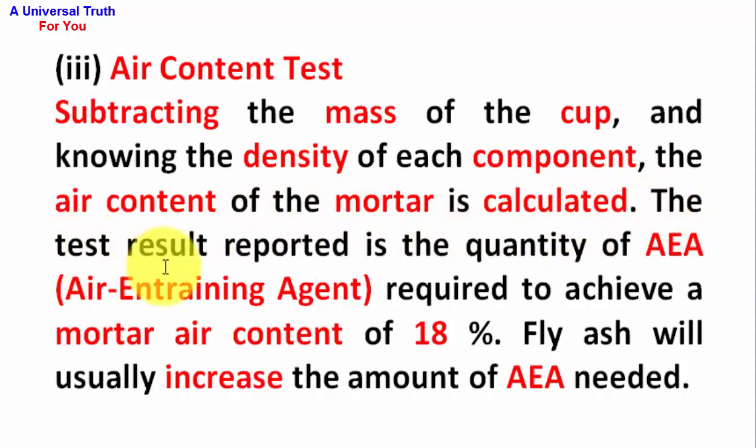The test result reported is the quantity of AEA required to achieve a mortar air content of 18%. Fly ash will usually increase the amount of AEA needed.